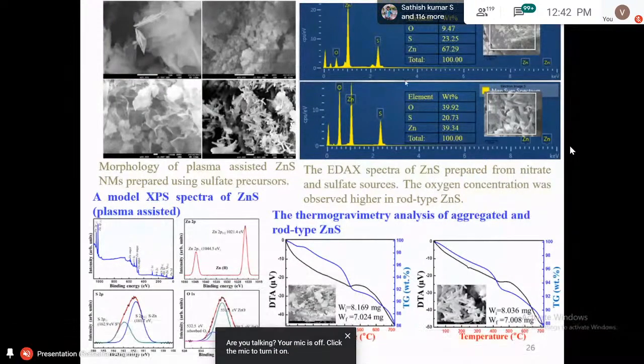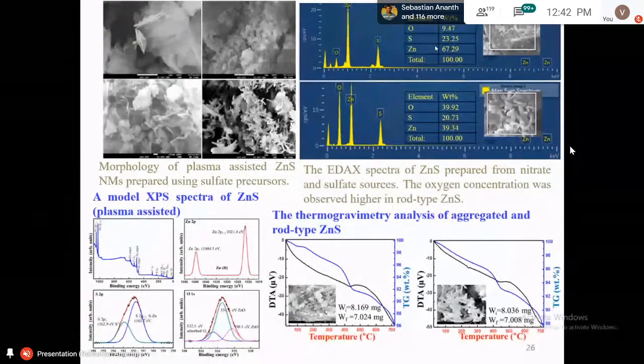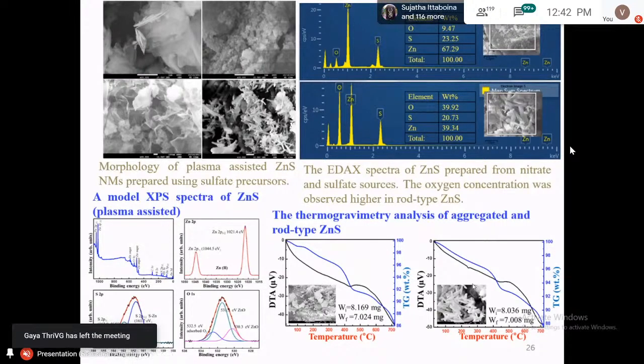And also we analyzed the EDX measurement. The prepared nanomaterials consist of only zinc and sulfur with minor oxygen, and no other impurities were found. And we checked the thermal stability of the prepared structures. We took two model zinc sulfides: one is the spherical kind, the aggregated structure, and the other a one-dimensional structure, for checking the thermal stability.